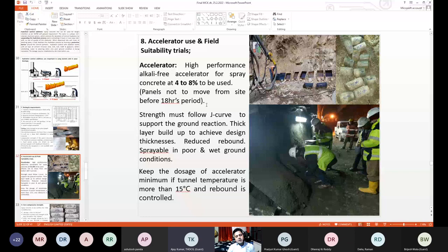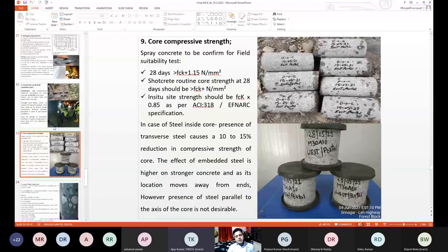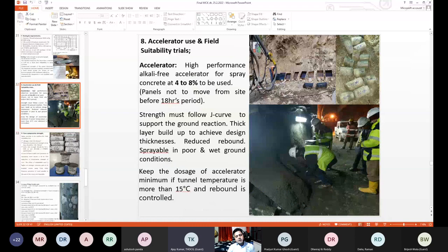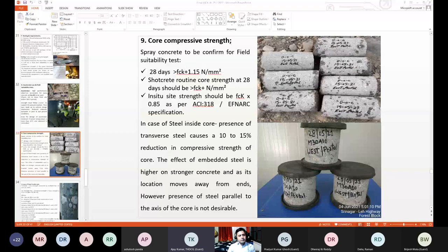Now, the core compressive strength. You know, the 28 days strength should be FCK plus 1.15 during the execution. The shotcrete routine core strength at 28 days should be FCK plus margin, like 30, 32, 33, it is okay. But the strength should be FCK into 0.85 as per ACI 318 EFNARC specification.